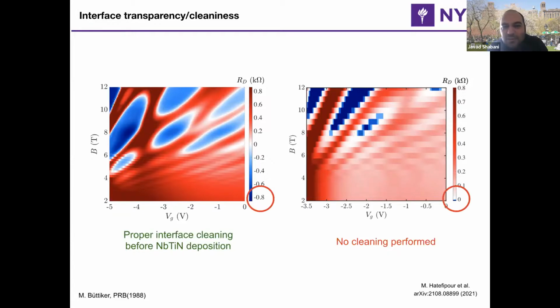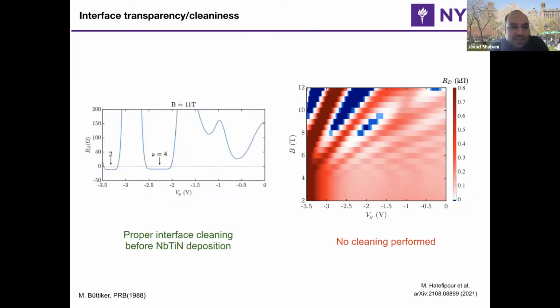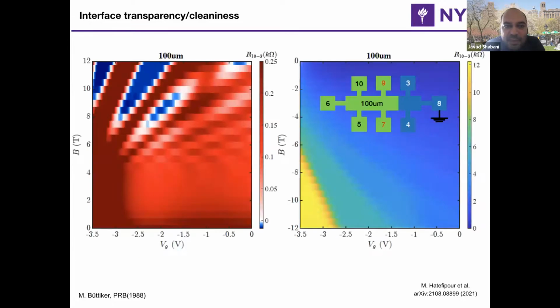In fact, if you do a line trace, let's say at 11 Tesla for this dirty sample, you can see that the resistance is on the order of 8 ohm or maybe 10 ohm, right? So same procedure, same sample, same wafer, but just not taking care of the interface. So this definitely tells me that the interface is important. And the fact that we have been able to get 20% is a result of actually making a really nice interface. So we did, actually, Antoine suggested that maybe where we ground the superconductor is important.